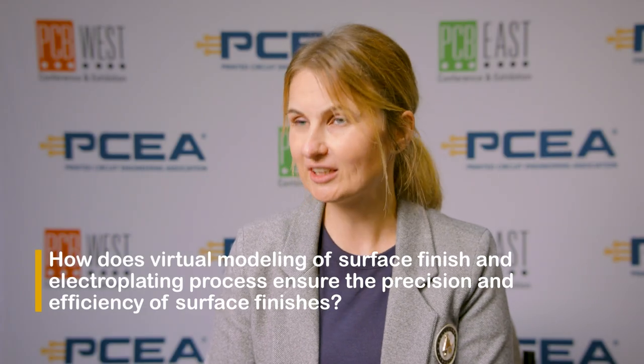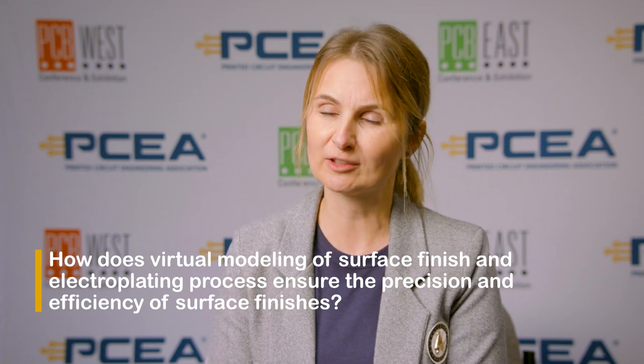Virtual modeling of the electroplating processes, and I'm talking here particularly about copper electroplating for the PCB, can allow us to have very good control over the plating process so that we can control how well we are depositing copper, and control the thickness and the coverage. And this analysis, virtual modeling, allows us to recognize what the over and under plating surface areas are, and how the current density distribution looks on the active surface areas before any actual plating process happens. So if we have any complex design, we can upfront evaluate how the plating process performance is going to look on this design. We can then also take some preventive measures towards process optimization and run our actual process by making sure upfront that it is adjusted in a much better way than we normally would do without having these virtual modeling approaches in-house.